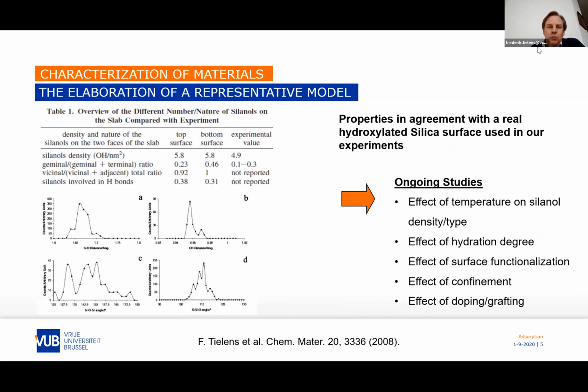So here I show you some experimental results that we used to make this model. It's mainly the number of silanols, the silanol density, which is directly related to the degree of hydration, and also the way it is synthesized. This degree of hydration is translated into silanol densities, but you have different types of silanols: geminal, vicinal, and isolated ones. They can all be characterized within a certain window of certainty, but what is sure is that there is a distribution among them, and this makes every silica characteristic.